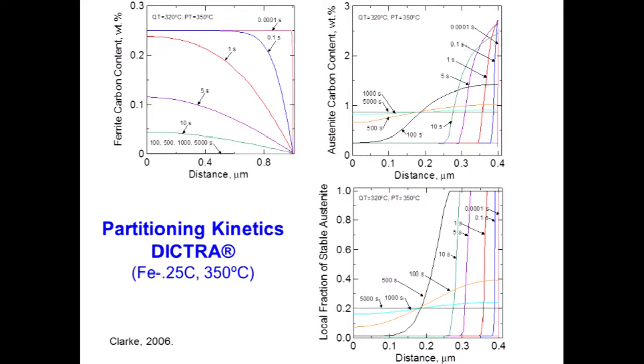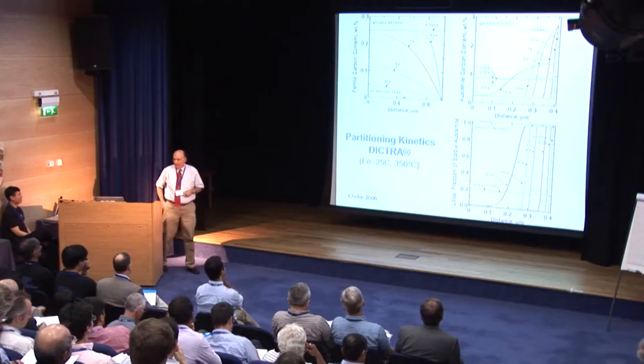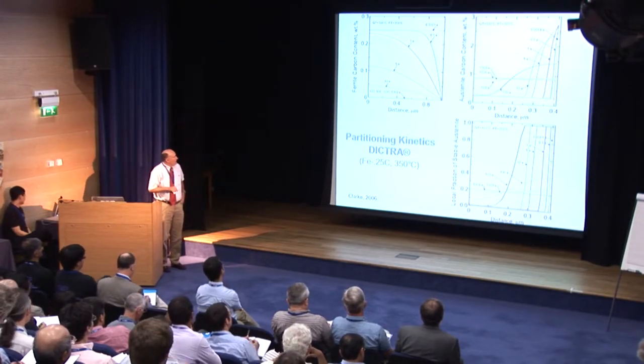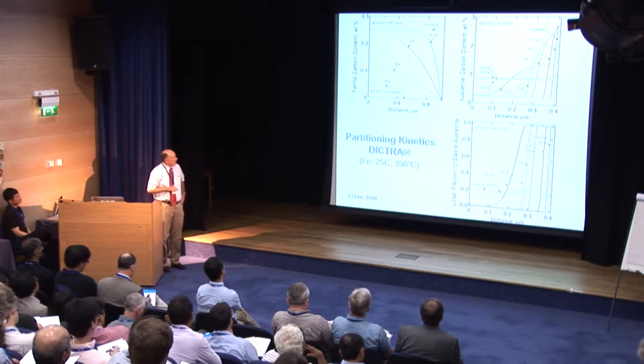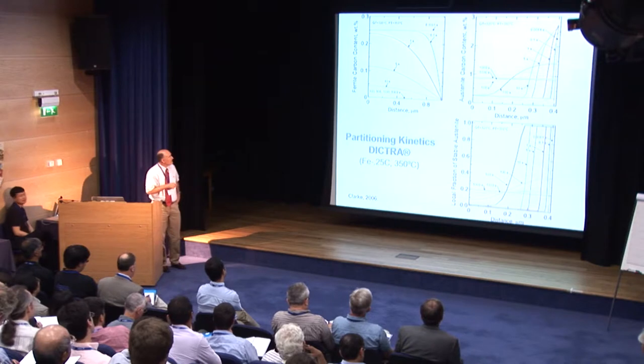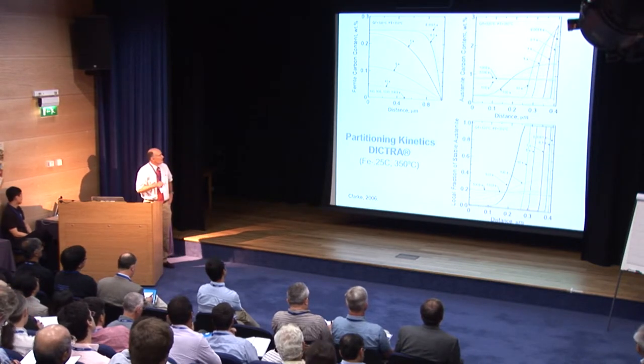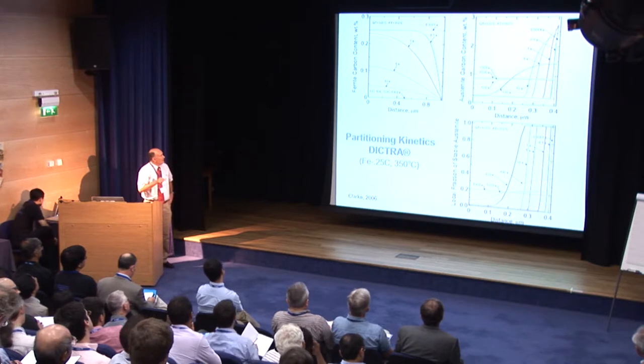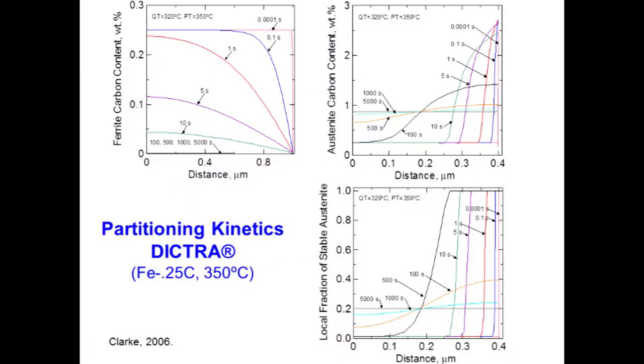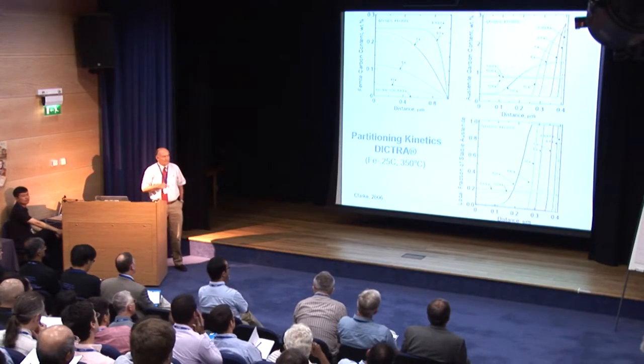Our original models looked at transformation behavior, and subsequent models incorporated some partitioning kinetics. These are some DICTRA models. You can see that the ferrite gives up its carbon rather quickly. It takes longer to equilibrate the austenite. What's interesting about that is that under certain partitioning scenarios, the austenite might contain most of the carbon, but with a non-uniform chemical composition gradient. We get some interesting effects then when we try to understand the stability of that austenite.